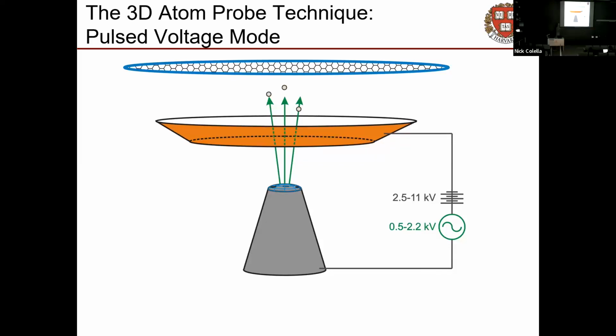So we hang out just below the field at which your sample explodes. This is a very exciting sort of measurement. And when it goes wrong, so does your sample. And then we give it little kicks. We can kick it with a voltage pulser and just kick it up over that field threshold, and atoms fall off. And that works pretty well.